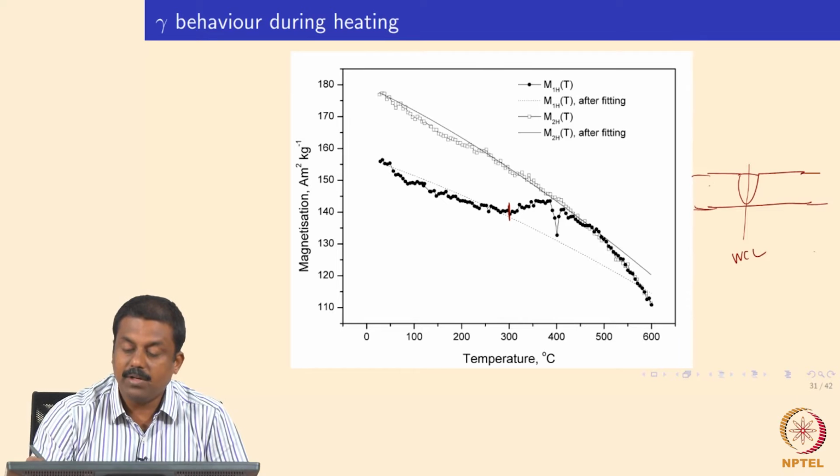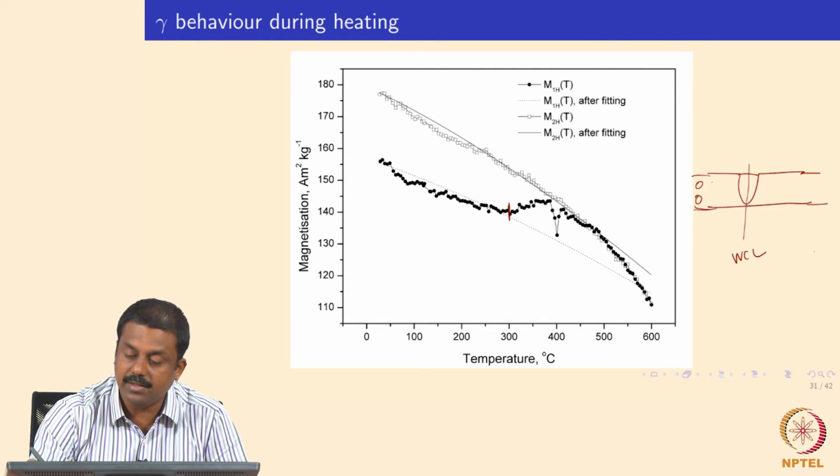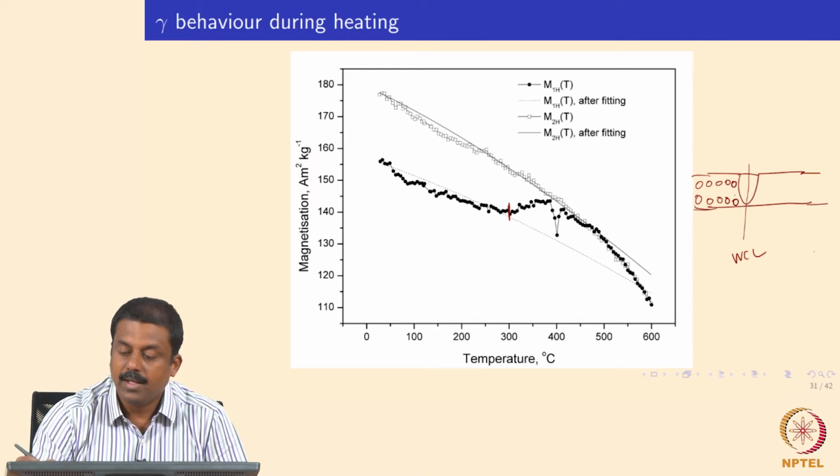So, if you want to measure the magnetic saturation, we need to take samples from the varying regions. For example, in the base material, in the subcritical heat affected zone, where temperature reaches below the critical intercritical temperature, and samples at the intercritical regions, as well as the fine grained and the coarse grained heat affected zone.